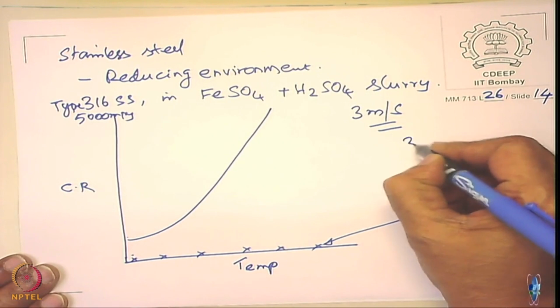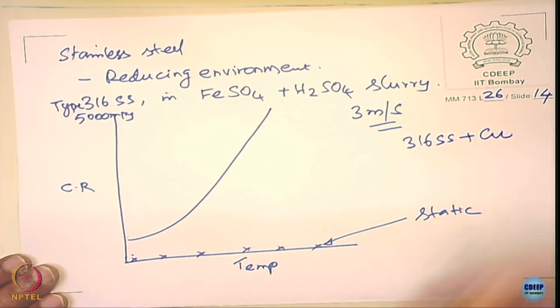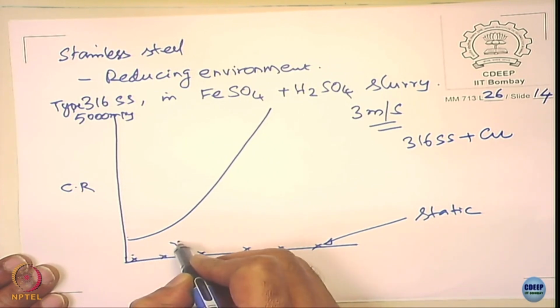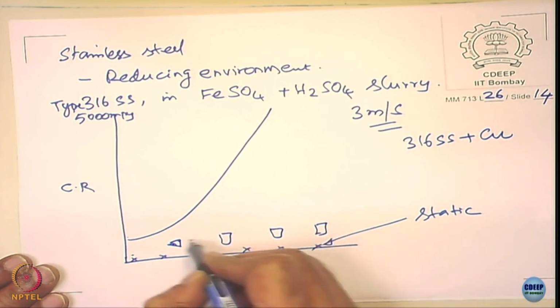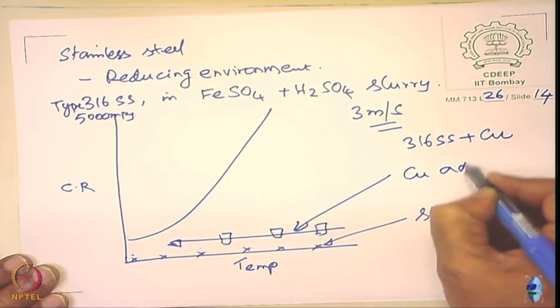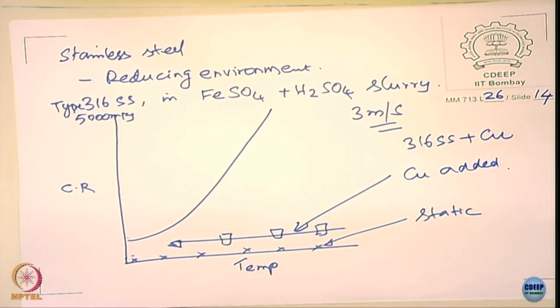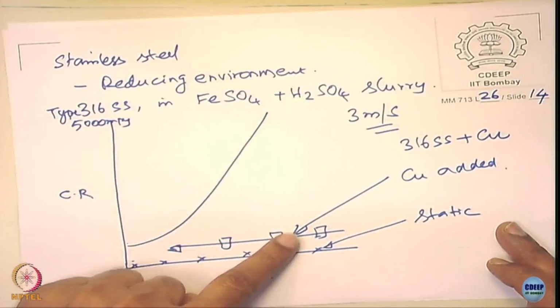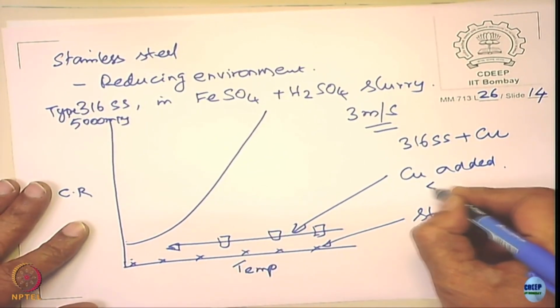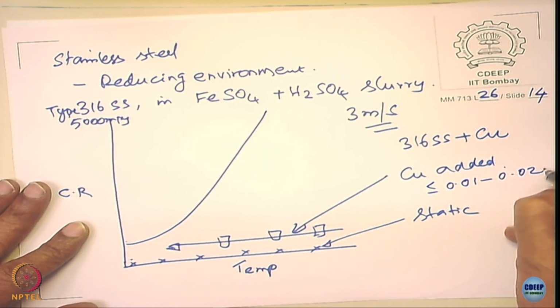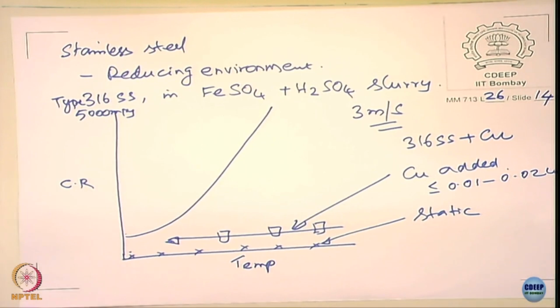But you take 316 stainless steel and add some copper to that, the corrosion rate drops. So when you add copper to stainless steel, the film forming tendency becomes very high. In fact, if you look at the material selection for sulfuric acid applications, the stainless steels have copper in them. So copper helps to form a stable passive film. So there is a significant drop in the corrosion rate, and these copper additions are all in terms of 0.01 to 0.02 weight percent, not a very large amount of copper content. It can happen.